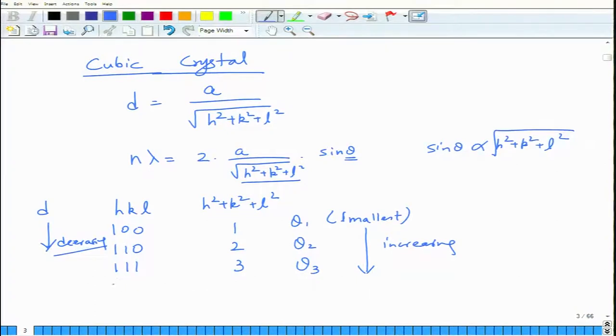So, 111, you can go to now 200, that will give you 4 theta 4, and then you go to 210, that will give you 5 theta 5, and so on and so forth. So, basically when you look at the X-ray diffraction for a cubic crystal, at least when you look at the X-ray diffraction peaks, they go in the order of increasing values of H square plus K square plus L square as a function of theta. So, as theta increases, H square plus K square plus L square increases.